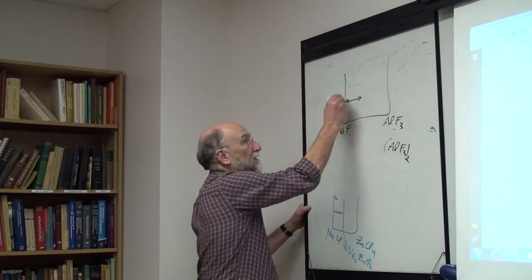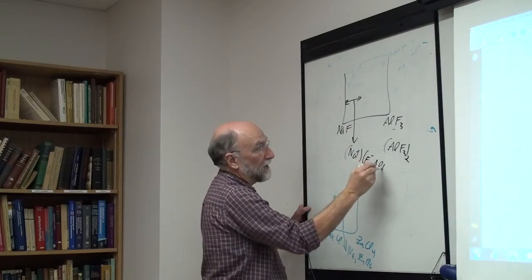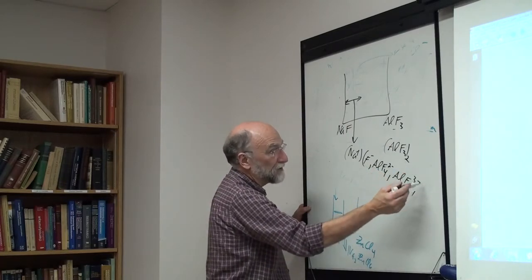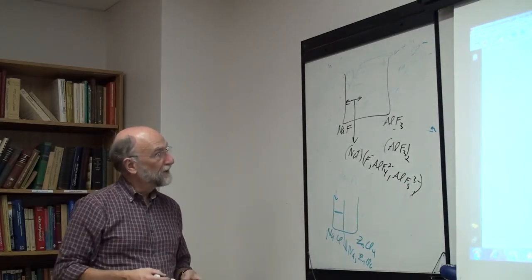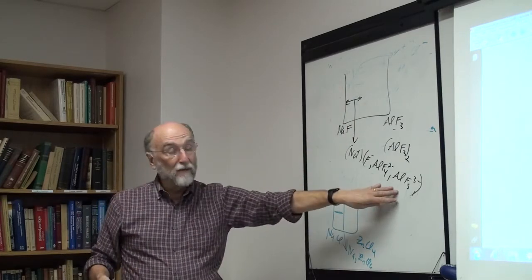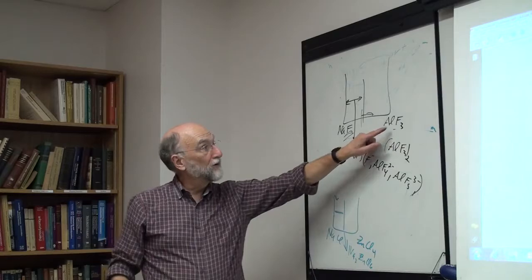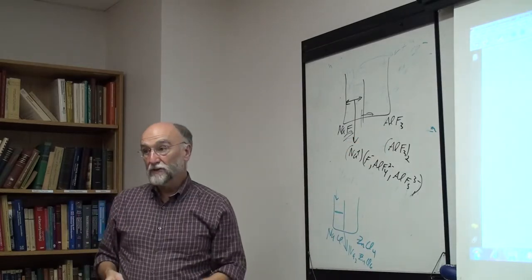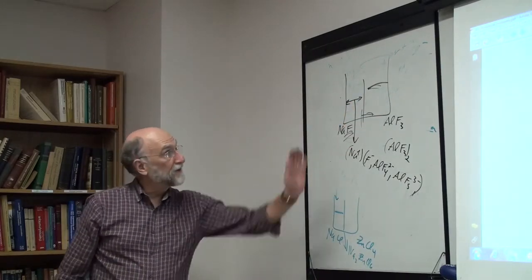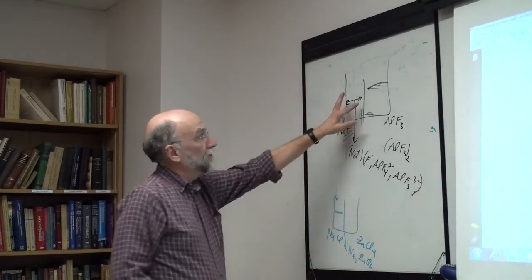But when you put it over on this side, then you end up with sodium ions, and over here you'll have fluoride ions, you'll have AlF4 ions, you'll have some AlF5 ions, and according to Patrice, you don't have any AlF6 ions, even though that's what people thought you had. So over on this side, up to AlF4, it's quite stable, low vapor pressure because it's become ionic. As soon as you pass a certain composition here, you don't have enough fluoride anymore, then you start to get molecules again and the vapor pressure goes way up. And you obviously can't electrolyze something over here because it's not an electrolyte, it's not an ionic conductor. You can electrolyze it over in this region. So that's the formation of cryolite solution.